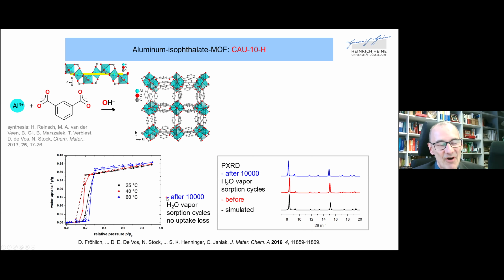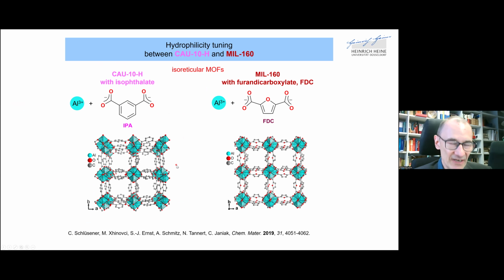We didn't do it for every MOF, because the time to run 10,000 cycles is a little bit longer, as you can imagine, than just 40 cycles. What is also nice about these aluminum MOFs is that there are so-called isoreticular MOFs. That means, as I just showed you, many of these aluminum MOFs have a very similar structure. Because of this, you can partially replace one ligand in a MOF with another one. So you get mixed linker MOFs, which keep the same structure as a monolinker MOF.